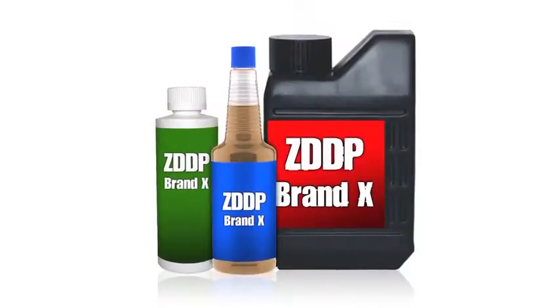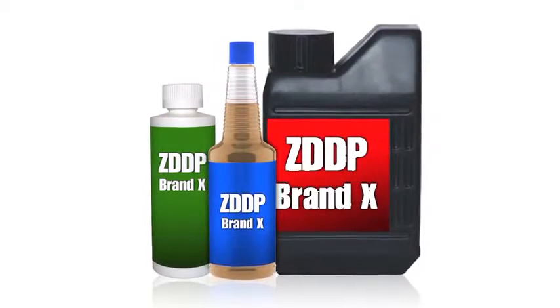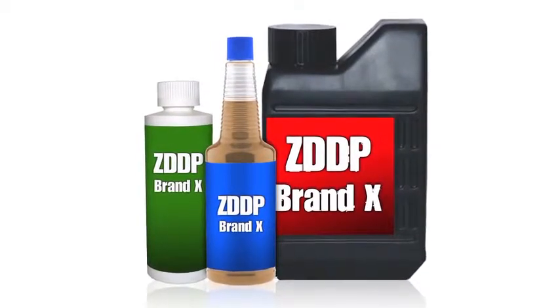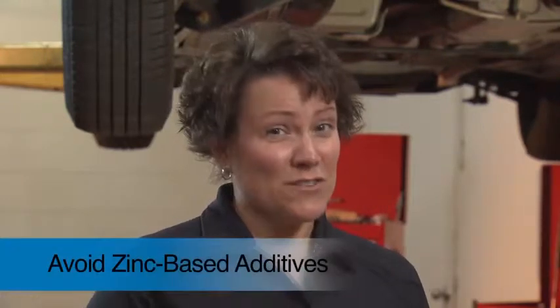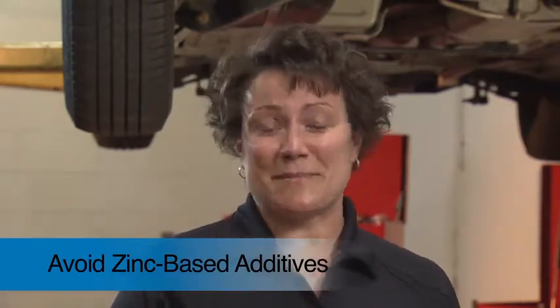Leaded fuel should never be used on a vehicle equipped with a catalytic converter, as the lead will quickly damage the honeycomb structure. Some performance enthusiasts use oil additives containing zinc, which is claimed to reduce engine wear. Problem is, oil companies significantly reduce the amount of zinc in their oil formulations specifically to prevent converter damage. So save yourself some trouble down the road by avoiding zinc-based additives.